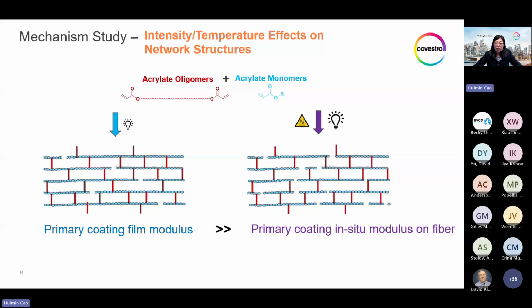And the high temperature and high intensity also have a significant effect on the network structure. Under normal conditions of moderate intensity and temperature, the network is rather complete, and some of the chain ends that are shown here are normal because all chains have intrinsic chain lengths, not infinite. But under a high intensity